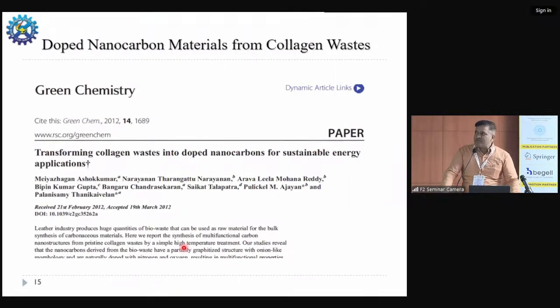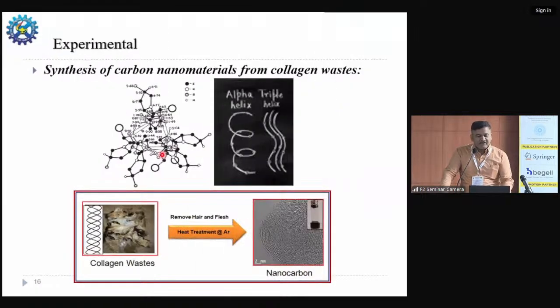In this example, what we have done is to take the collagen waste without any chromium and convert it into self-doped nanocarbon materials for sustainable energy applications. We take the skin, remove the unwanted material like hair and flesh, and subject it to high temperature treatment, from say 500 to 1000 degrees Celsius, in the absence of oxygen. Therefore, we are able to convert it into nice nanocarbon materials.